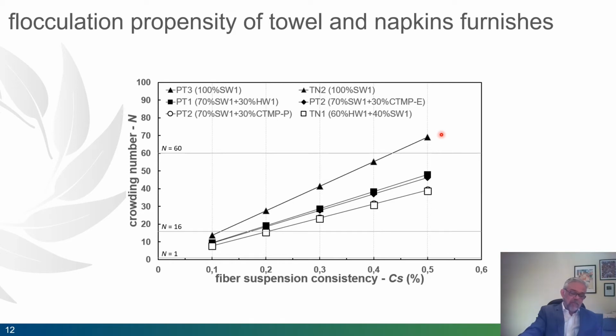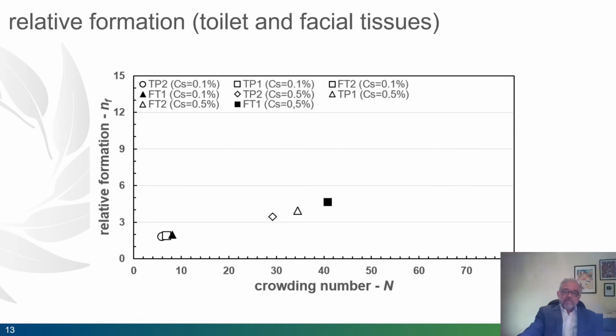Furnish compositions employing CTMP have lower flocculation tendencies even when mixed with softwood, since CTMP tends to have shorter fibers and higher fiber coarseness. These results emphasize the impact of fiber morphology and stock consistency on flocculation potential of tissue paper furnish that directly influences web formation uniformity, which will be discussed in the next slide.